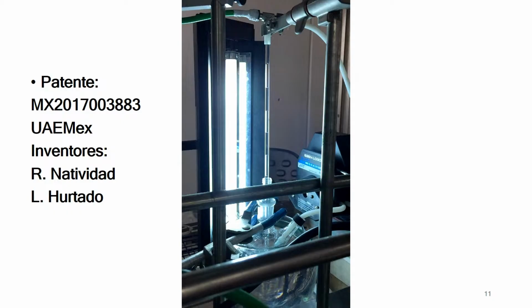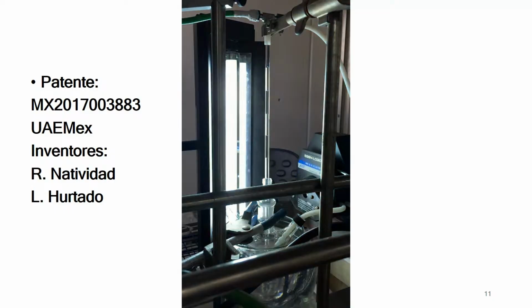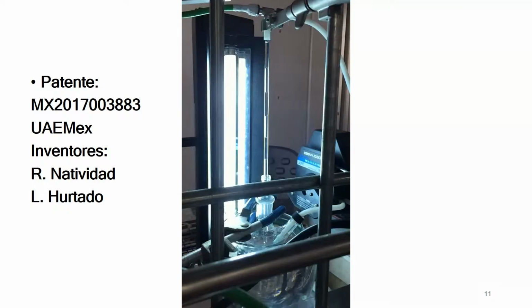Here is the photocapillary reactor. It consists of a capillary, so you have to use a light source. This is the visible lamp that we use, but you can also place a UV lamp here. And then you have here a T connection where you are feeding the CO2 gas and the liquid phase, and they enter the reaction zone. And then here is a container where it is again taken by a peristaltic pump and recirculated. So at the end, it's a batch reactor in terms of the inlets and outlets, a semi-batch reactor, but it doesn't have stirring, or at least not macro stirring.